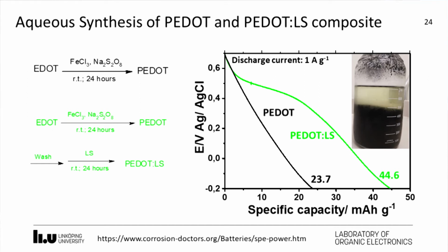persulfate. Then this product was washed carefully and mixed with lignin sulfonate for some time to get the PEDOT lignin sulfonate composite via an ion exchange process. Here is a picture of the products. It is ready for screen printing, drop casting, and other large-scale applications. Also, this charge plot shows that lignin sulfonate was successfully incorporated with PEDOT nanoparticles, as shown by the increase of the charge capacity from 23.7 to 44.6.